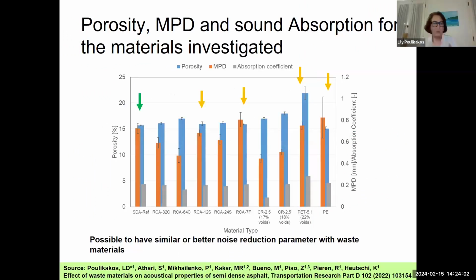I mentioned that we need to also look at acoustic performance. So the acoustic performance is affected by porosity, by mean profile depth that has to do with the surface texture, and acoustic absorption. So here you see these three parameters for our reference and for all the mixtures that we have used. And several of these that I'm showing with the yellow arrow have very similar values to our reference. So it's possible to have similar noise reduction properties with the waste materials.